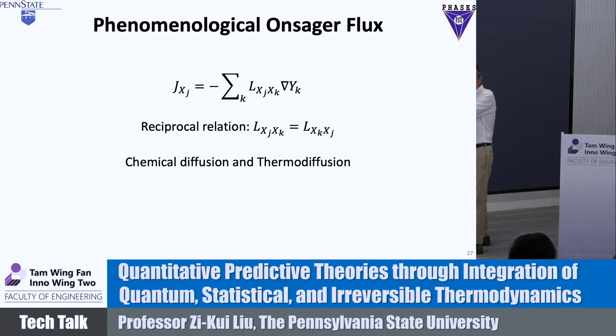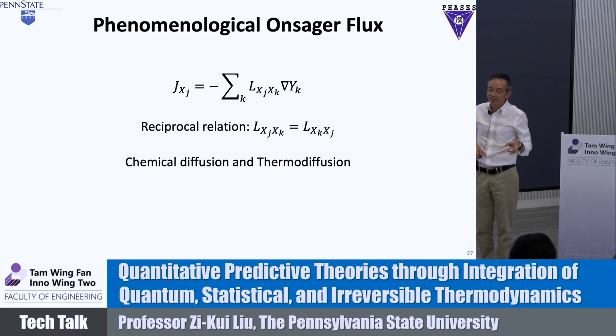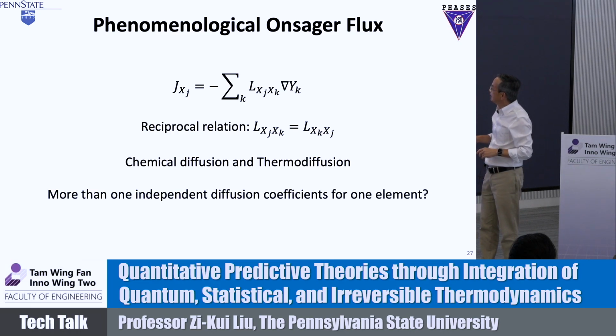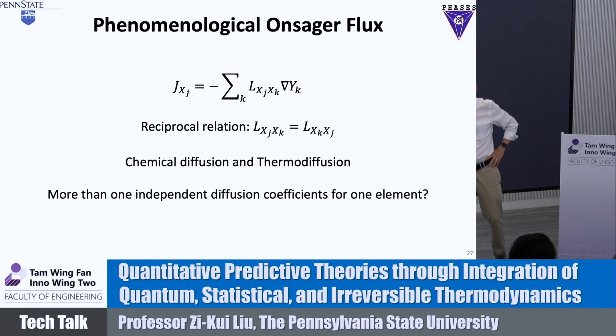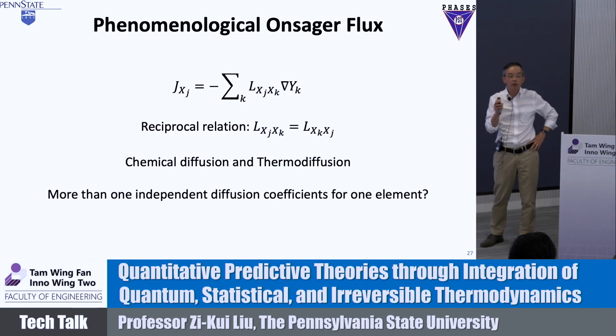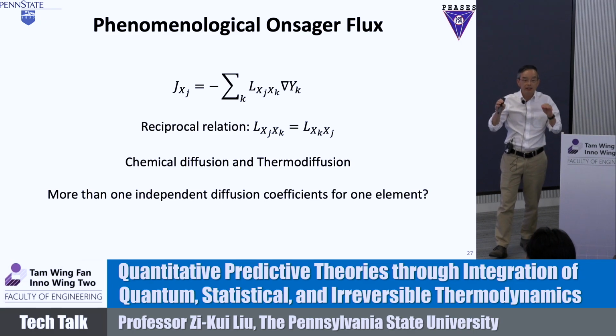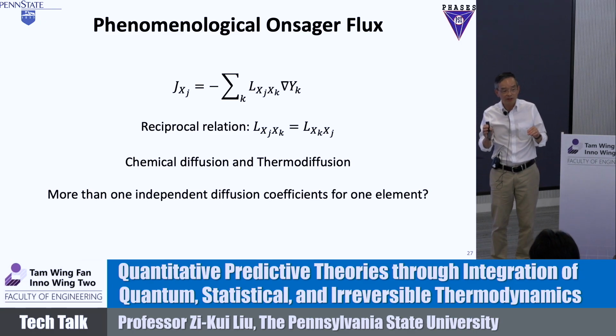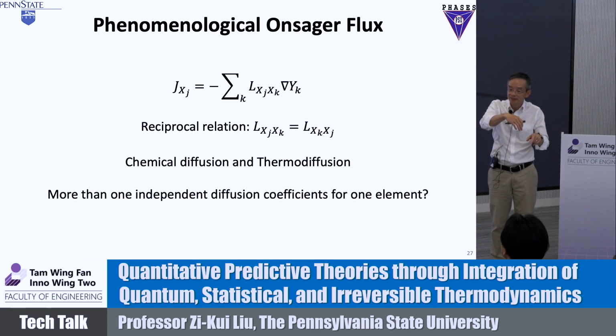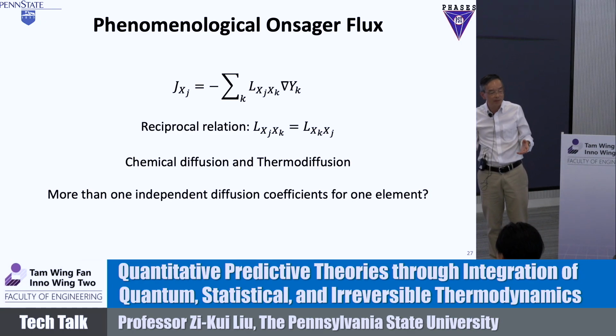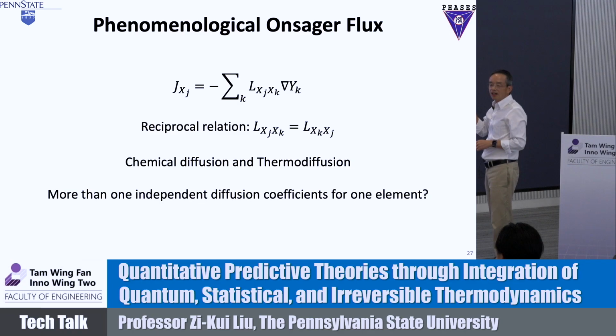That's where I got into the problem. I'm doing chemical diffusion, and my host was doing thermal diffusion. He told me there are two diffusivities, and they're independent. Then I said, more than one independent diffusion coefficient for one element? That's simply wrong. There's only one diffusivity for one element. What it means is the atom has to overcome a barrier. That's it. How it is driven doesn't matter. It's only the atom jumping from one side to the vacant site. That's the only mechanism for diffusion. There's no other mechanism. It's only the driving force or the barrier, how much they are. So I did not believe the Onsager equation to start, but I could not prove it.